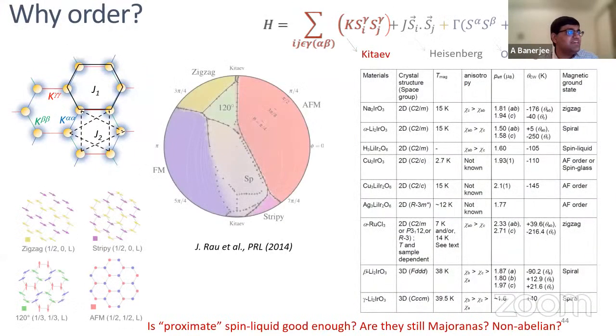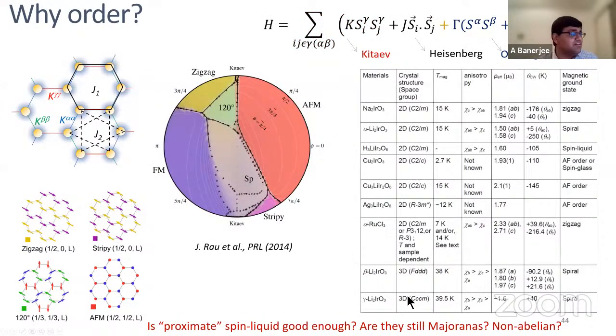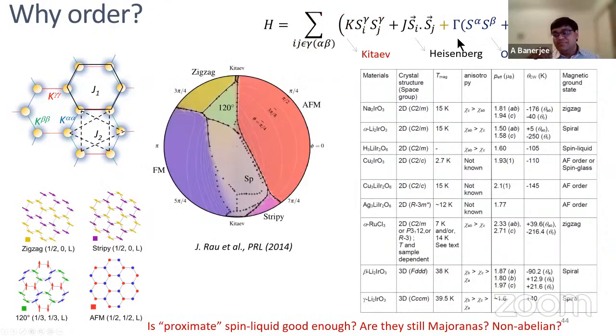One question that is faced by the community, and a lot of research is going on, is why does the system order? If you just had these Kitaev interactions, then the system should have been in a quantum spin liquid state. But in a real material, you really can't just have this one interaction. You basically have some second order Heisenberg interactions, all kinds of parasitic interactions, gamma interactions. And when you have that, you basically can get many kinds of long range ordered ground states.